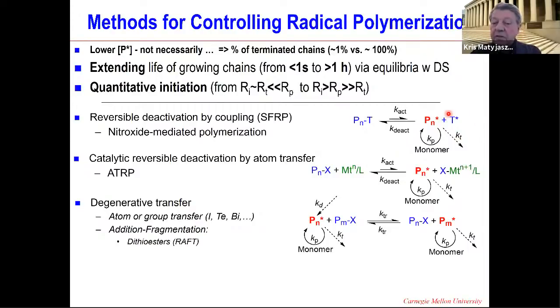We can use, for example, stable free radical, nitroxide, something that Craig developed many years ago in the form of TIPNO, or classical TEMPO derivatives. You can also use here organometallic species, and in that case, it would be cobalt(II) derivatives and formation of organocobalt derivatives, chemistry very similar to vitamin B12. Or we can do that with this dual catalytic system consisting of activators and deactivators in ATRP. Or you can apply also degenerate transfer. In that case, a radical can take an atom like iodine or potentially dithioester or some other group, and then itself become dormant and unblock the other one to be able to propagate.